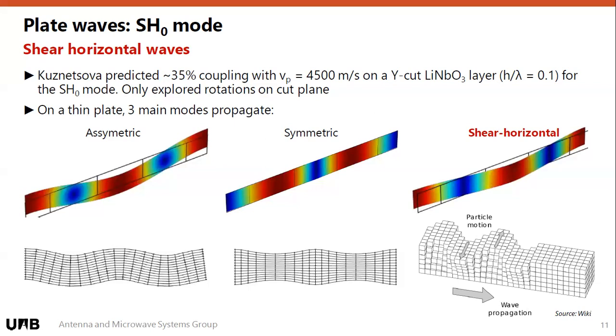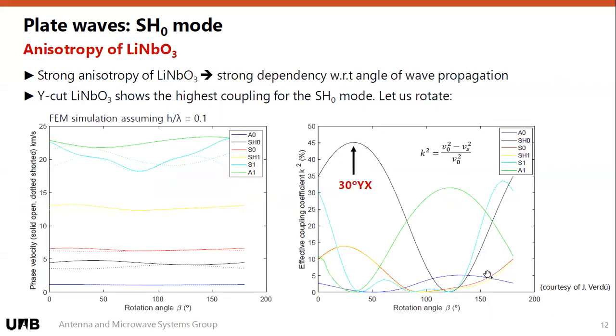So we're going to choose the shear horizontal mode as Kuznetsova predicted because it offered a really wide, high coupling. And we started doing some FEM simulation that was performed by Jordi Verdú here, so I took these figures from him. There's one thing you need to account for, as we're playing with piezoelectric materials, so they should be anisotropic. But LiNbO3, or lithium niobate, is super strongly anisotropic.